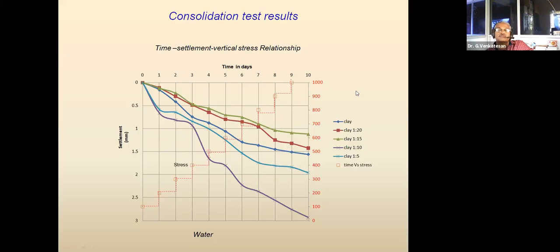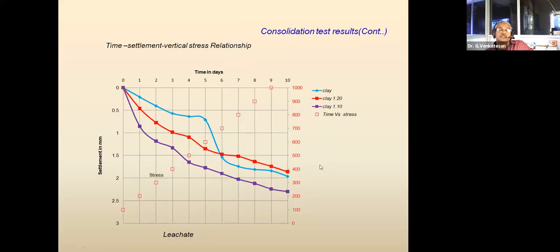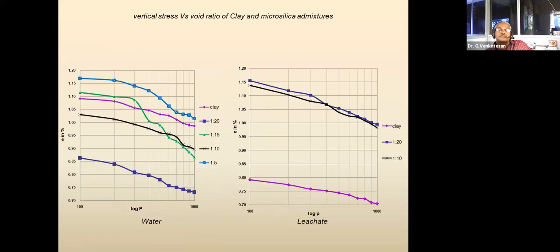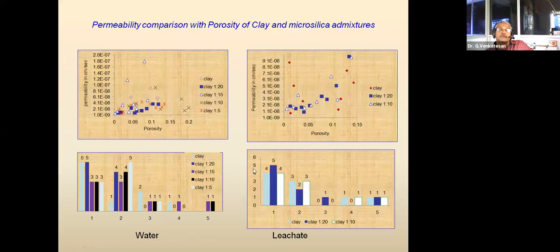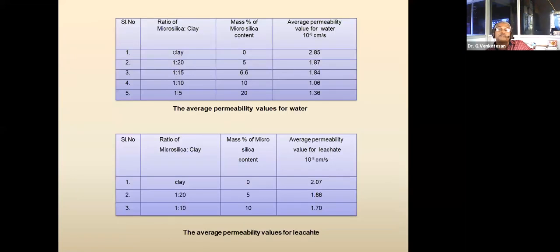So the various ratios. This is the time-settlement and vertical stress relationships for time in days of settlement. Vertical stresses with various ratios of clay and microsilica admixtures, and the log p value will be there here. So we compare permeability versus porosity. It is 5 ratios in water and 3 ratios in clay. So we obtained the final average permeability values for water: 2.85, 1.87, 1.84, and 1.6.